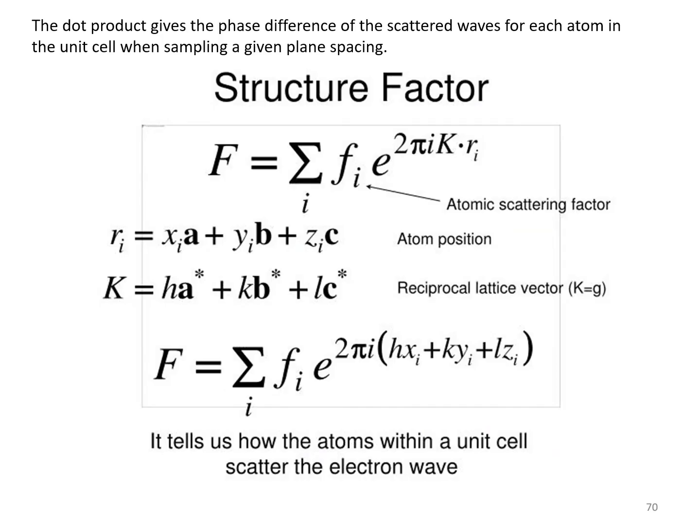And I also talk about structure factors. The thing that people use to characterize structures, especially powders, is called a structure factor. I'm not going to go into the details here, but what this amounts to is we have a position of an atom in a unit cell and a vector which describes the scattering off a given plane of atoms, and a factor which is the strength or the intensity of scattering from an individual atom.